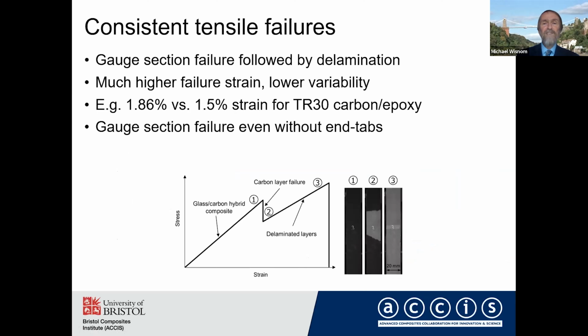So in this case here, with this carbon epoxy, we get 1.86% strain compared to about 1.5% with a more conventional test. So this is, I think, a very promising way of doing improved testing. It's very easy because you don't have to tab the specimens. I guess the only drawback is you're measuring failure strain, not stress. And also you do have to apply a small thermal strain correction, but it's not very large.